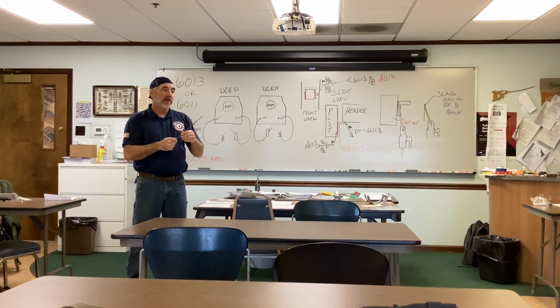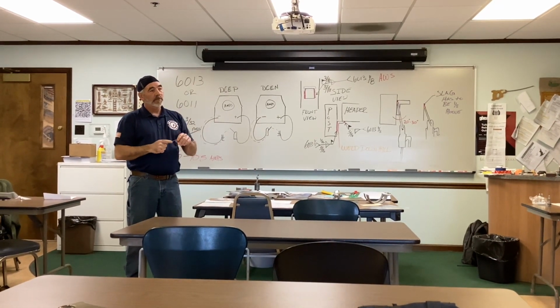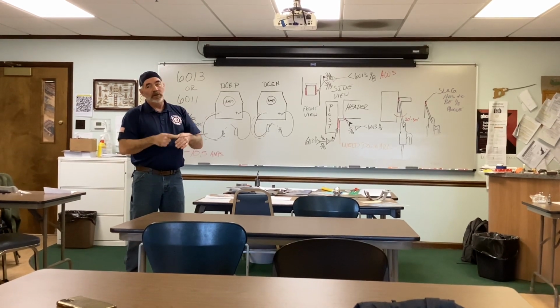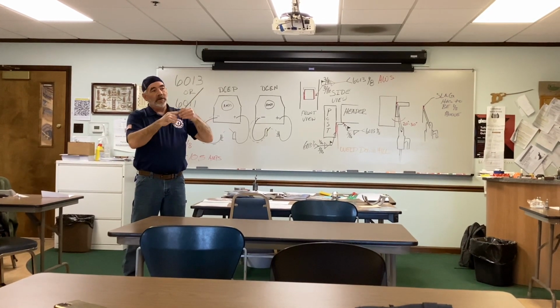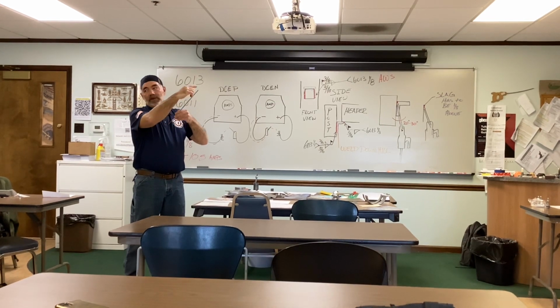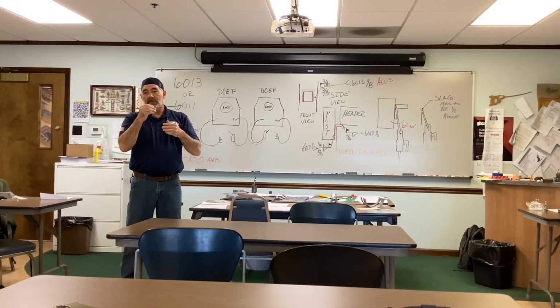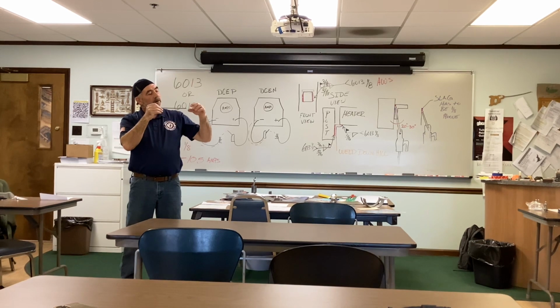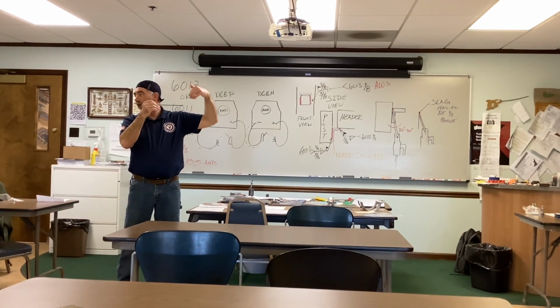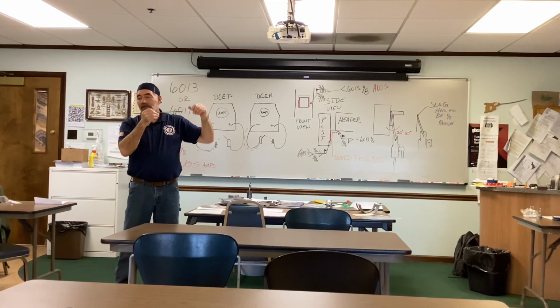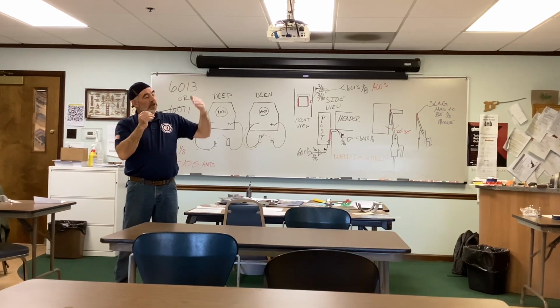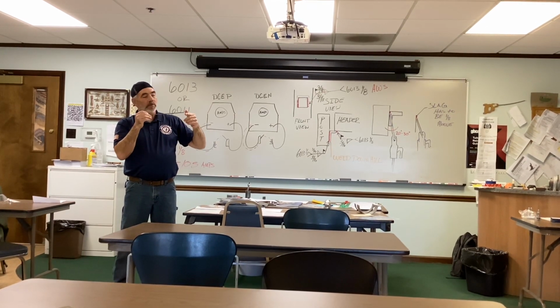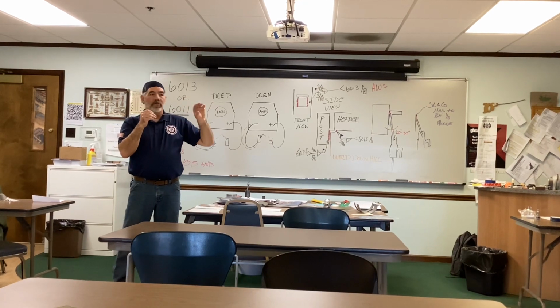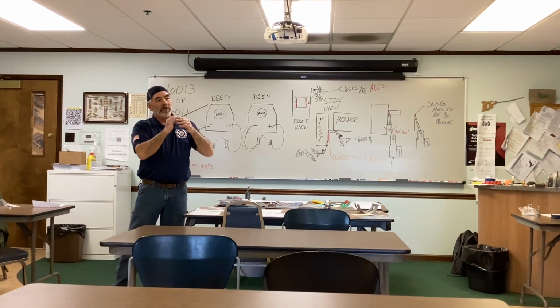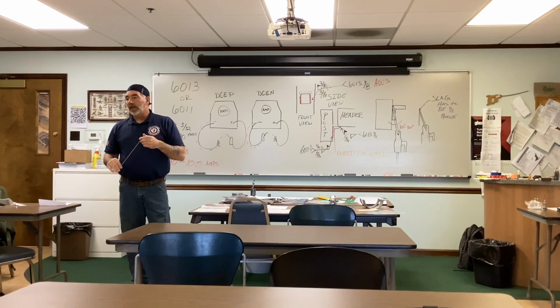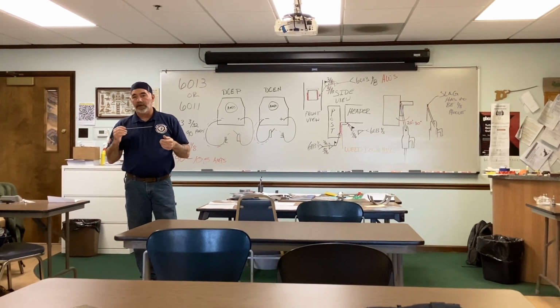And that's another thing. When you weld 6013 or 6011 on a vertical, you generally go downhill. You don't go uphill, because if you go downhill, the heat's going to stay below instead of being on top. When we do 7018 vertical, as we go up, believe it or not, the heat builds up in front of your rod and makes the steel hotter. So when you're welding thin sheet metal, you don't want to be going up vertical. As you build your heat up, it actually starts blowing through on that thin steel. So that's why we go downhill. With 6011 and 6013, you can manipulate downhill.